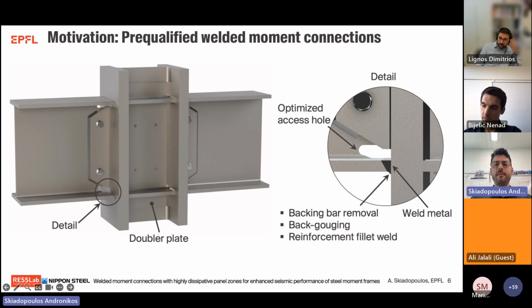This connection typology features an optimized access hole geometry to minimize stress and strain concentrations in this region, and therefore to delay the onset of fracture at that region, and also a weld metal with increased toughness requirements. Finally, with regard to the welded detail, after the execution of the complete joint penetration weld, the temporary backing bars that are placed in that region should be removed.